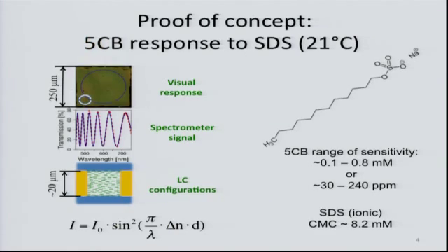So imagine you have a single liquid crystal cell that contains a freely suspended nematic liquid crystal film. And these green dashes represent the orientations of the liquid crystal molecules that make up this film. And it so conveniently happens that water aligns the liquid crystal molecules in a direction that is parallel to these interfaces. So water here is shown in blue. Now, when we add surface active molecules in the water, they will bind to these interfaces and they will change the alignment.